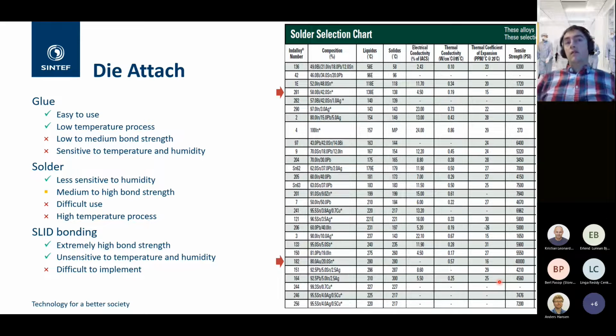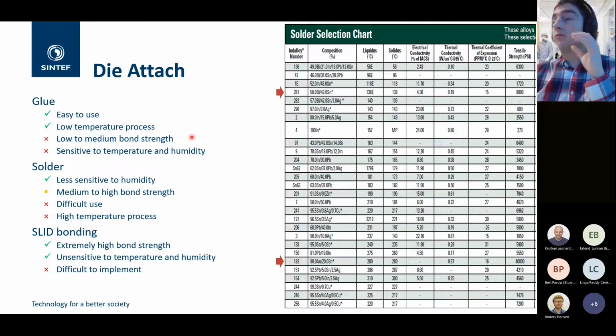We were evaluating 3 types of bonding, let's say, from the easy one, that is of course glue, in which we basically want to use an epoxy-based glue to attach it to the mechanical part. The glue is of course easy to use. It's a relatively low temperature process. The bond strength is kind of good, but is not optimal, of course. And furthermore, it's degraded with the temperature and humidity in the environment. So it's not extremely good for a high performance and stable sensor.